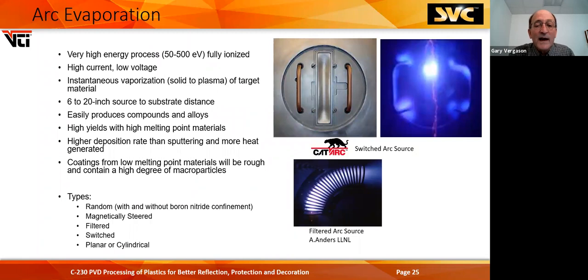Arc evaporation, we're not going to talk too much about arc. In the pictures over here, you can see what our switched arc cathode looks like, door open and under operation. We use discrete anodes, which boosts the operating voltage substantially in our process and gives us a higher energy coating. So we get better coatings at lower temperatures. It's a very high energy process, 50 to 500 eV, and it's a fully ionized plasma. It's high current, low voltage. We actually use welders for power supplies.